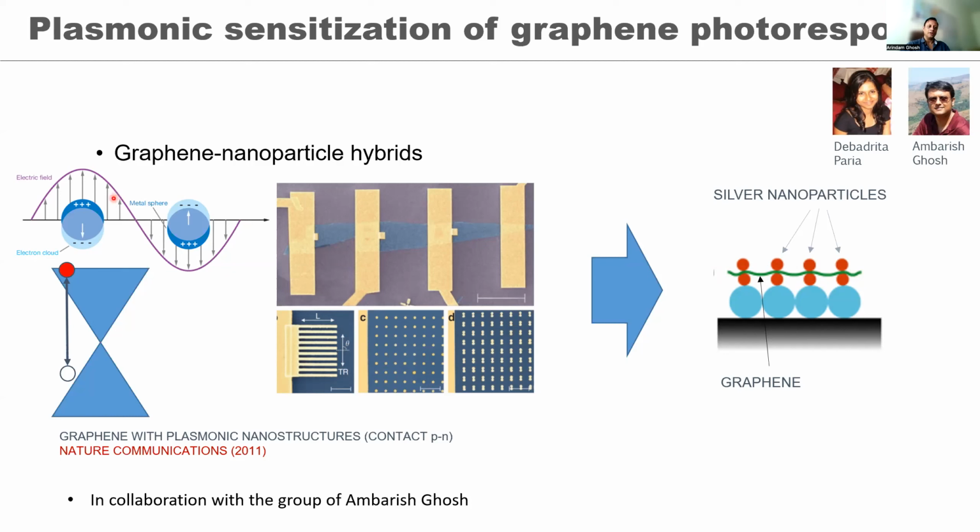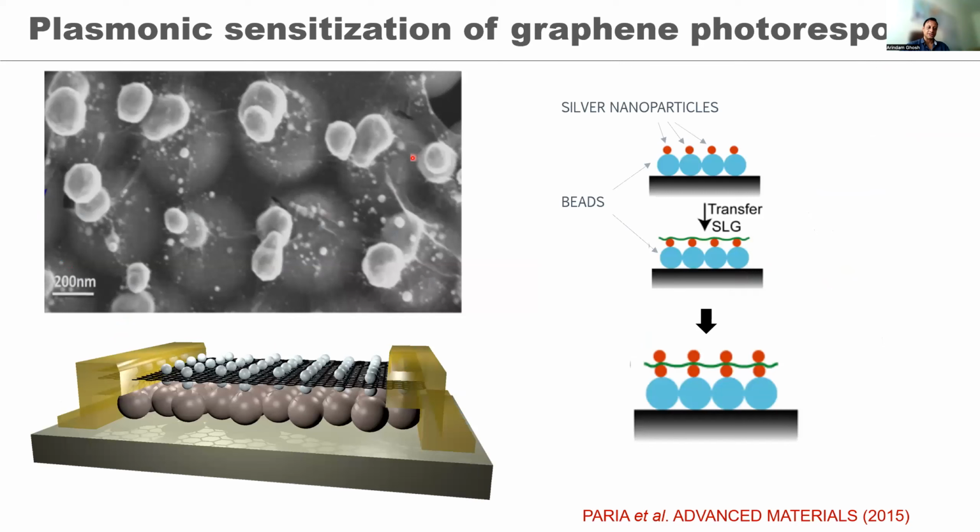And then the whole goal was essentially to see if the plasmonic surface plasmon resonances can create a large electric field at the graphene. And this is really the ultimate large electric field, because you can think of two nanoparticles separated by the smallest distance possible, which is the graphene thickness. And that can lead to a very large optoelectronic plasmonic activity. Turns out this is the typical structure that Ambarish could create using glancing angle deposition.